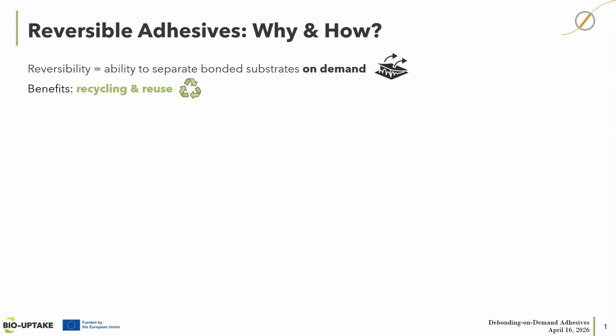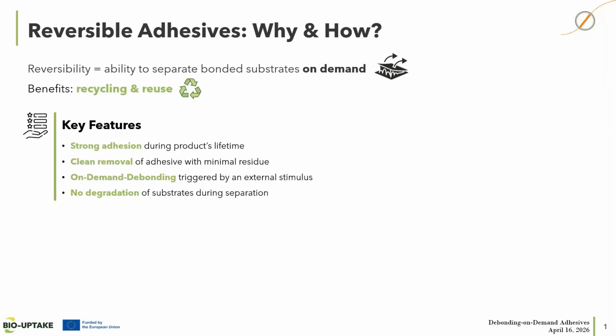So the debonding on demand means that two substrates can be strongly bonded during their lifetime, but separated intentionally when required. So this is particularly important for recycling and reuse because the classical permanent adhesives are not able to [allow recycling] of multi-component materials. So the challenge here is to have two opposite needs. First, a strong adhesion during the use, and secondly, a clean removal without damaging the substrates.